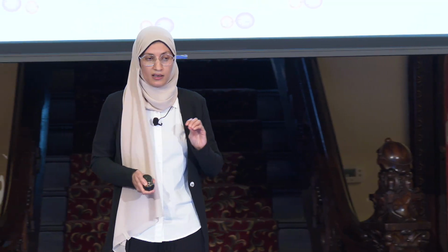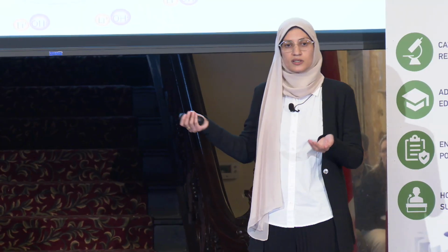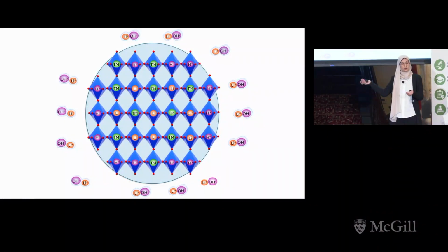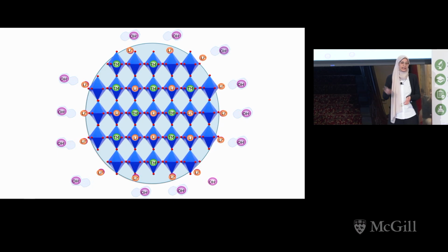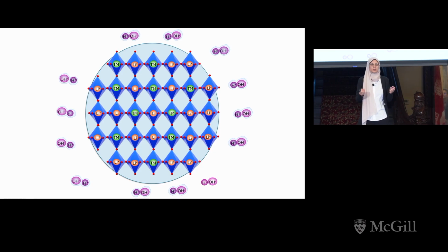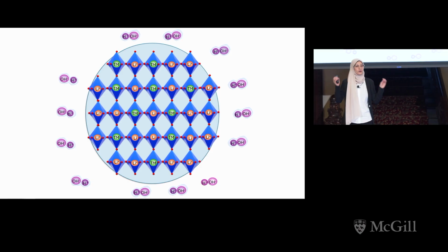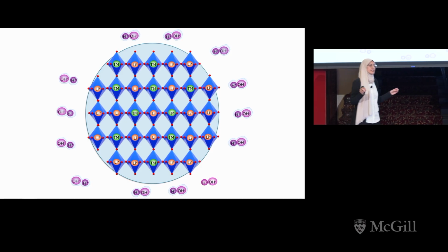And indeed, instead of washing the material in pure water, what we did is that we washed the material again, but this time in a highly concentrated lithium hydroxide solution. So we washed the material with a highly concentrated lithium solution in order to let lithium leave the solution and jump back into the structure. And this is what happened. And when we tested the material, we found that indeed we got our lithium back. So now we have our marshmallow particles with our lithium back in the structure, the material is ready to go.